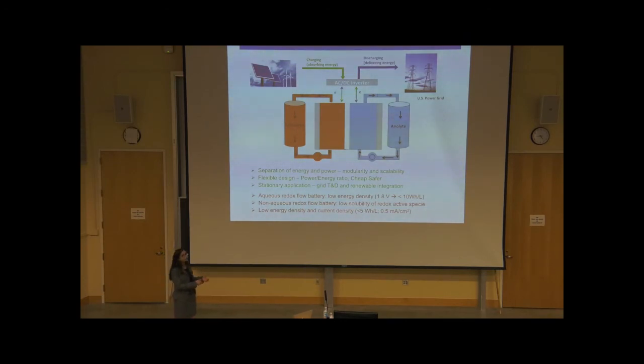separate tanks. So a typical redox flow battery contains two separate liquid reservoirs, typically a catholyte and an anolyte, and typically vanadium is used for both the catholyte and the anolyte. And then pumps are used to flow this catholyte and anolyte into the cells. And when an external source such as PV supplies the power, we oxidize vanadium 4+ to vanadium 5+, which releases an electron. Then this electron travels to the outer circuit and reduces vanadium 3+ to vanadium 2+. And these two electrolytes leave the battery in a charged state and